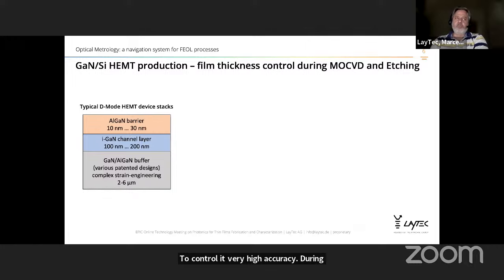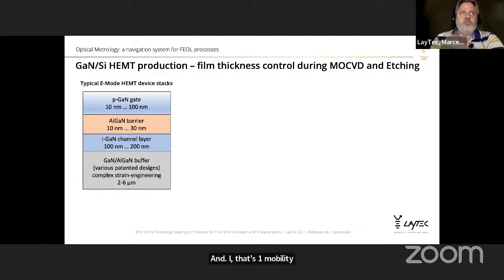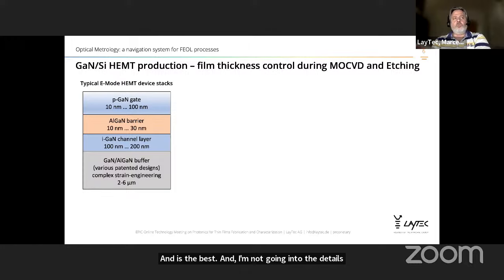So basically, there are two main types of devices here. One is this D-mode HEMT, which is the one that I show here, where you start with a GaN buffer to do strain engineering, directly grown onto the silicon. Then you grow an intrinsic GaN channel layer, and then an AlGaN barrier. And this would be the D-mode HEMT, high electron mobility transistor. If you add another step on top of it with the p-GaN gate, then you get an E-mode HEMT device. The difference between E-mode and D-mode is that this is enhanced mode, the other one is depletion mode. I'm not going into the details here, but most of the technology now is going toward E-mode because it allows you to produce transistors that are normally off.